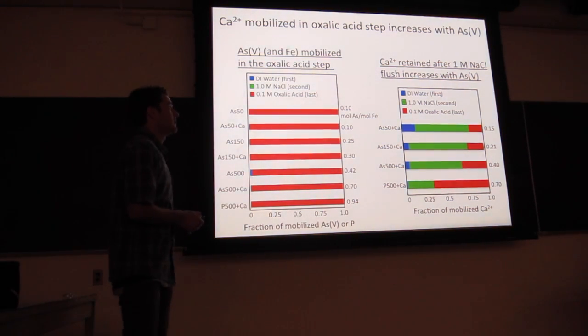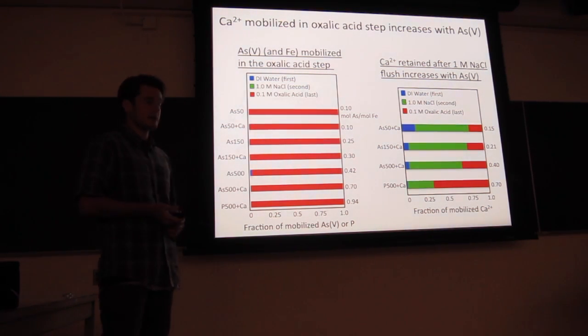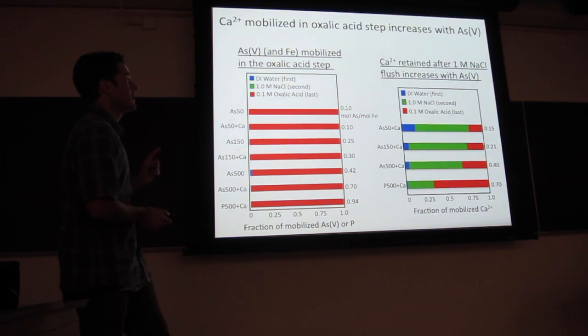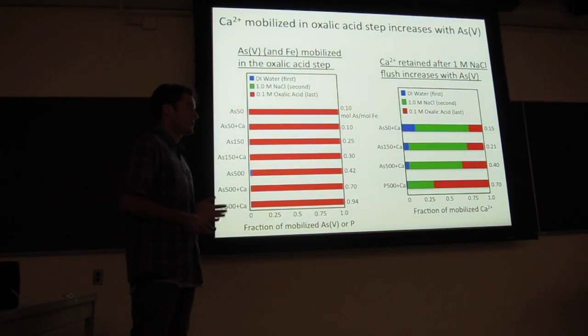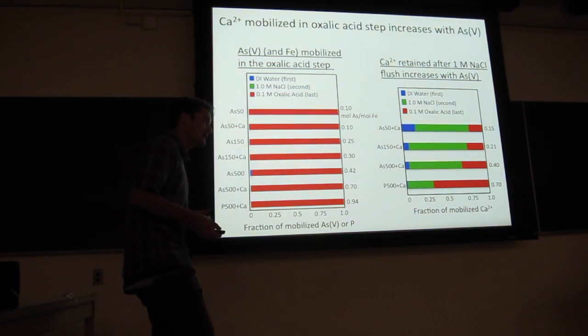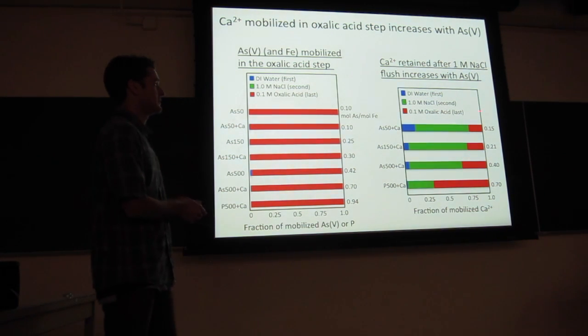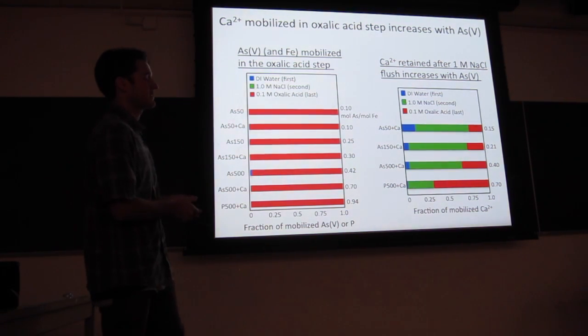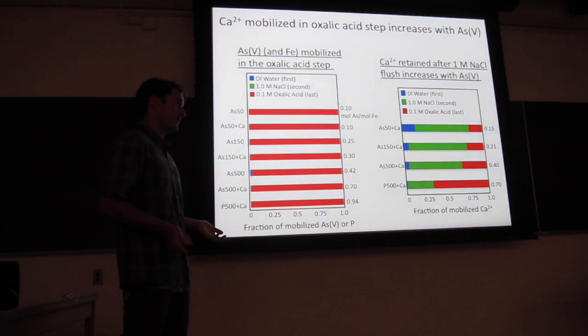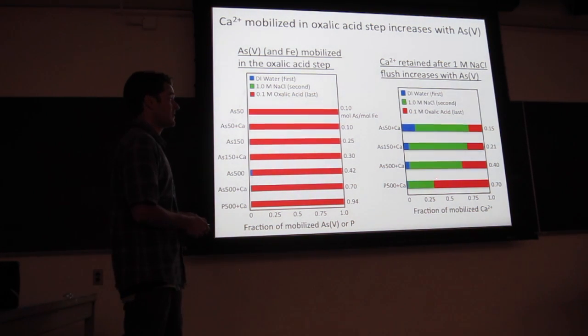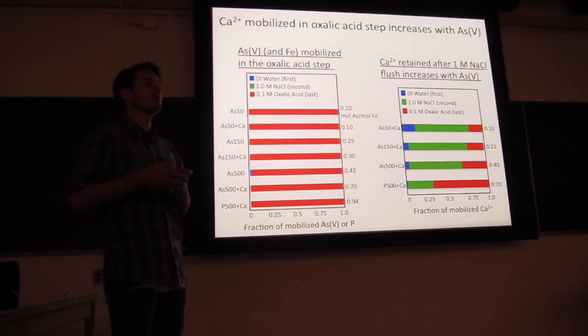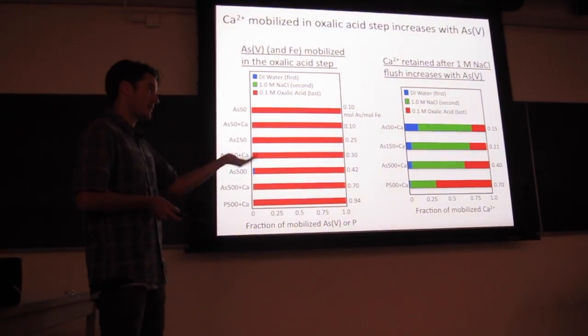Calcium, on the other hand, is mobilized both in the sodium chloride step and in the oxalic acid step. But there's a trend that calcium retained after the sodium chloride step increases with increasing oxyanion. So you see that trend here. And consistent with most of our other data, we see that this interaction between phosphorus and calcium is stronger in the phosphate series than it is for the arsenic series. So there's more strongly sorbed calcium in the phosphate series than the arsenic series.